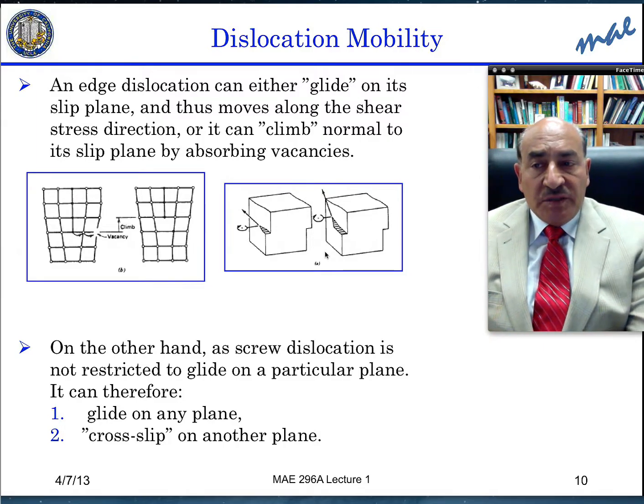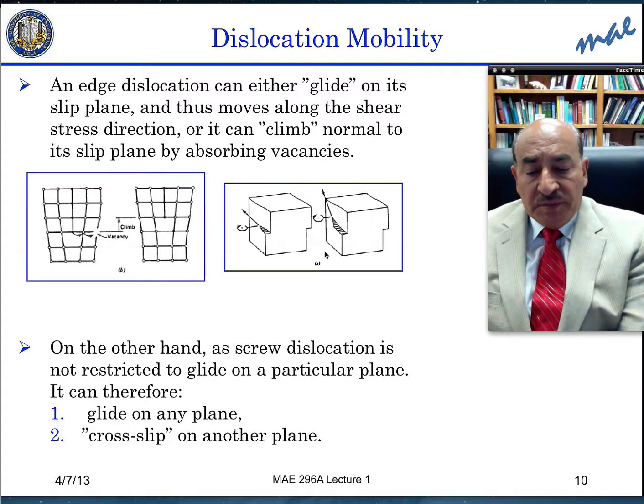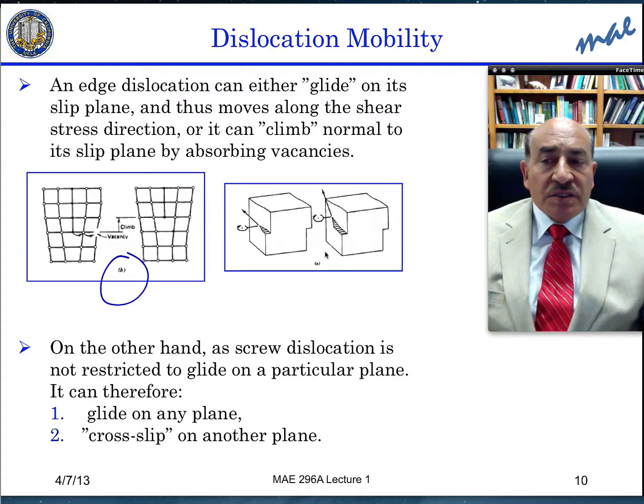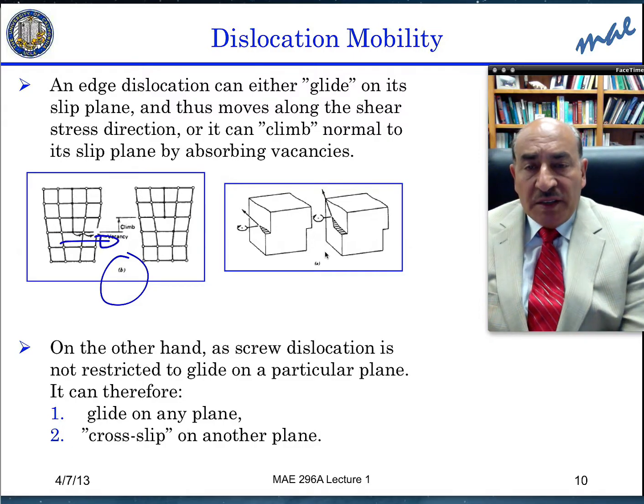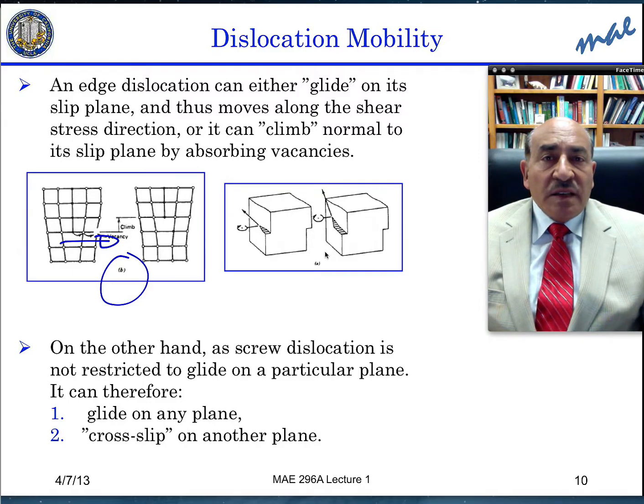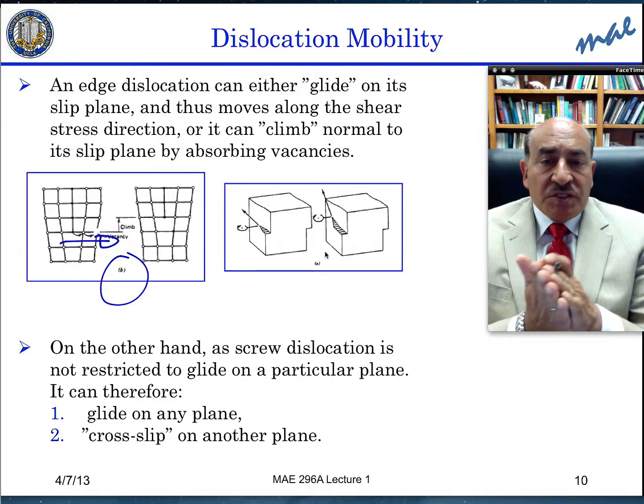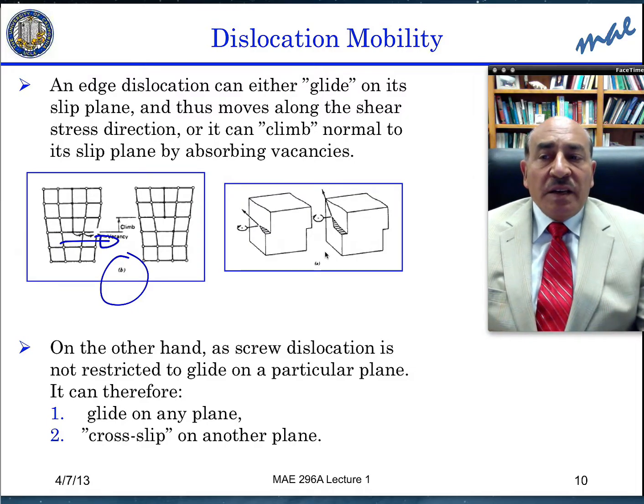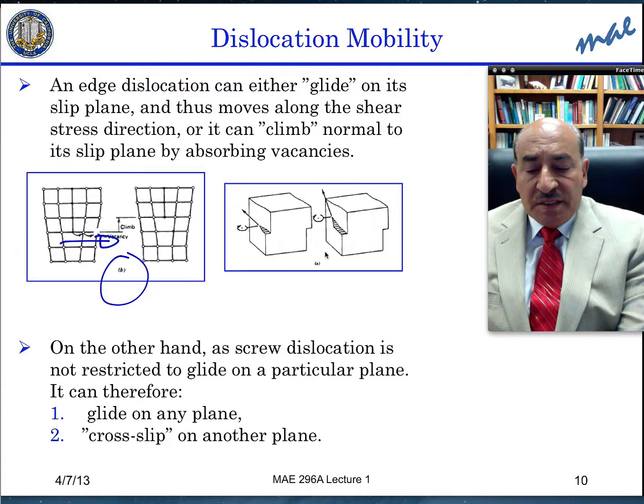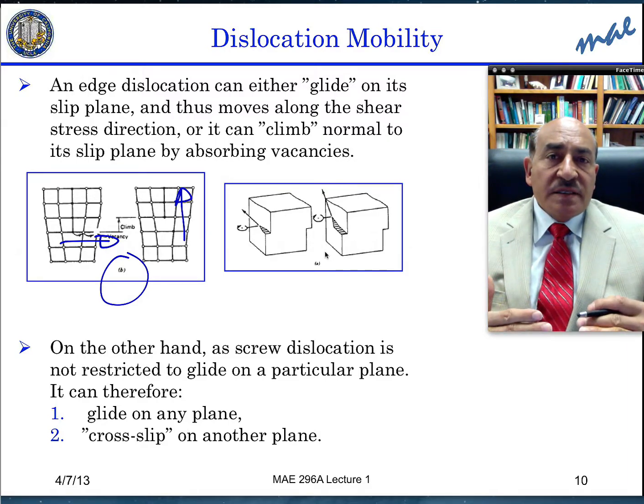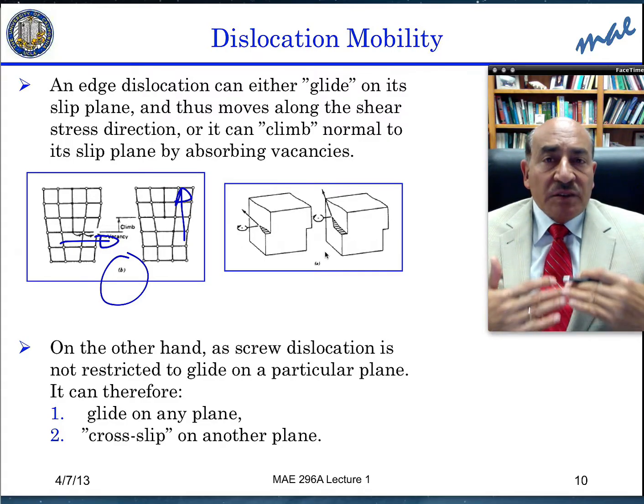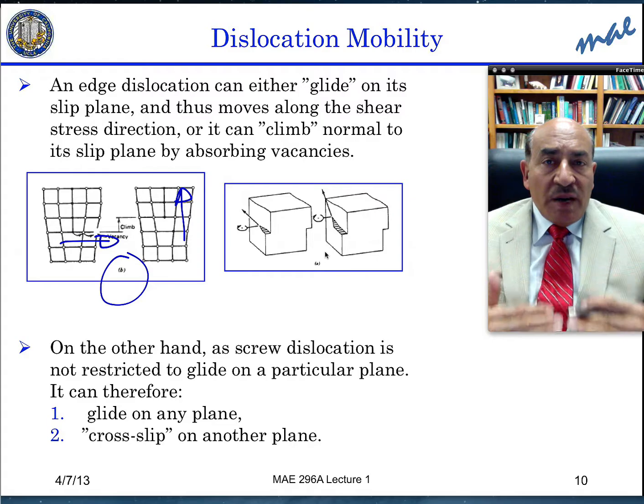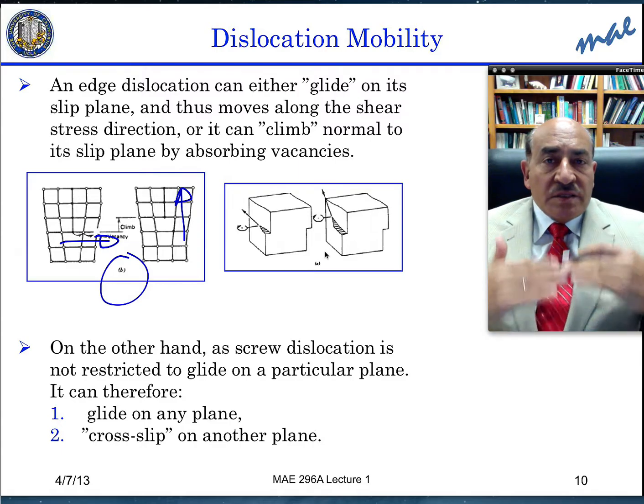For example, if you look at the left here, you have an edge dislocation, and if this edge dislocation moves on its glide plane, it produces slip, like a shift of atomic planes. If the edge dislocation absorbs vacancies, it will move up, because once it absorbs vacancies, the atoms are removed, and the row of atoms that delineates the bottom end of the dislocation no longer exists, and therefore the dislocation line shifts up.